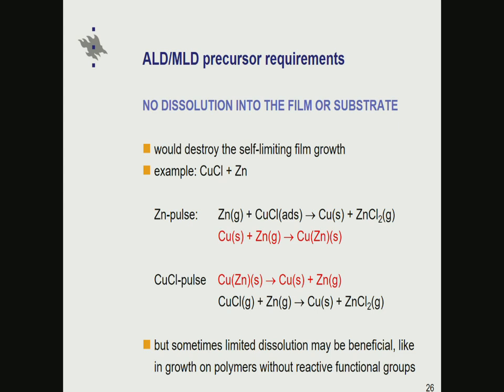So far so good, but once we have metallic copper there, we actually start observing brass formation. Zinc dissolves into copper and forms brass, but this is not stable, so that during the following copper chloride pulse, zinc is diffusing out from the copper. So the film itself is a zinc source, and it reacts in a CVD manner with the copper chloride.